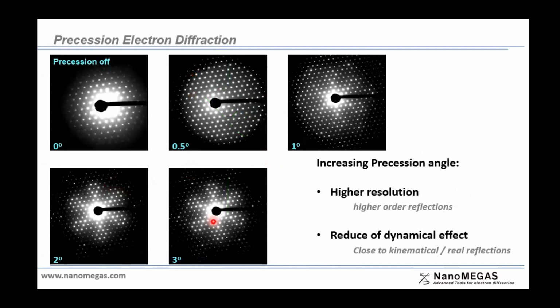So here are some diffraction patterns of a mineral without precession and with some angles of precession from 0.5 up to 3 degrees. And you can see that even with 0.5 degrees of precession, we have far higher order reflections, so we can see more reflections far from the center. So we increase the resolution, and then as we go up in precession angle, you see that we also have some change of the intensity of the reflections. And the reason is that we reduce the dynamical effect when precession is applied. So we go closer to kinematical intensities, or closer to intensities that you obtain also with X-ray. We will never have pure kinematical intensities, but we are at least approaching more kinematical intensities.